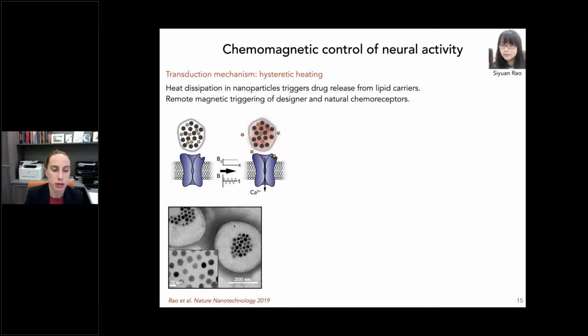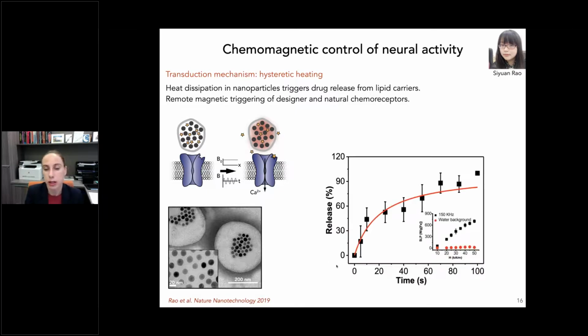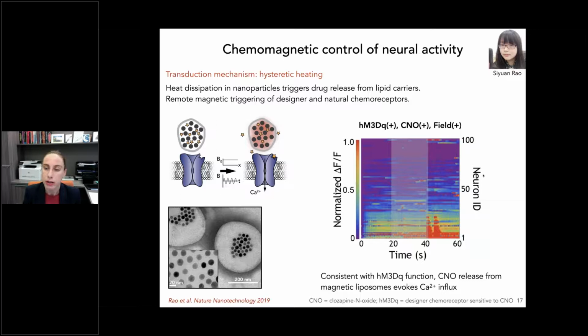So here is a transmission electron micrograph of our magnetic nanoparticles introduced into the core of the liposome along with a small molecule. And we can demonstrate to ourselves that indeed application of the magnetic field allows us to release these payloads, here shown through a release of a dye, and that release can be controlled either through different time period of application of the field or through different magnetic field magnitude and other parameters. And this work was led by a talented postdoc, Siyuan Rao, who is now a professor at the University of Massachusetts. And then we can apply this method to, again, control neural activity.